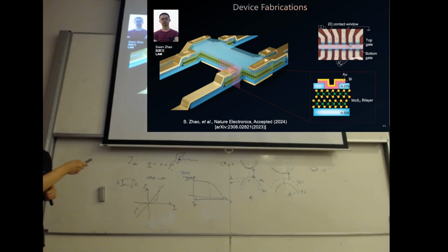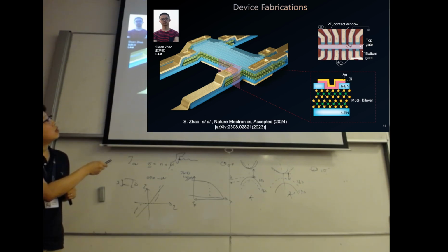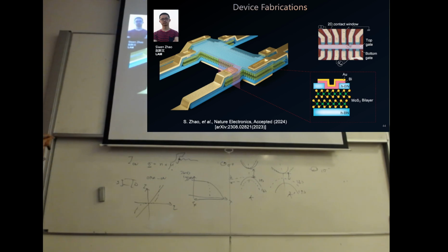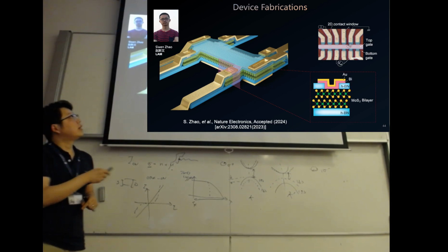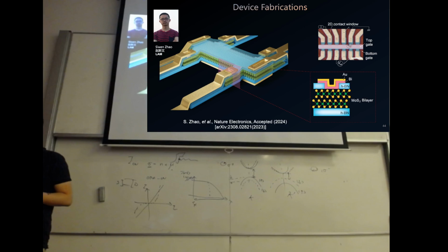With this small black color, you have some color contrast, because there is no hBN in this small window. That's why you have a color difference in the contact area. And the third thing is you should never use an e-beam evaporator. We don't know why. You have to use a thermal evaporator to do the evaporation of bismuth. Combining the three, that is glove box, window contact, and thermal evaporator, you'll have ohmic contact like a charm, down to very low temperature.